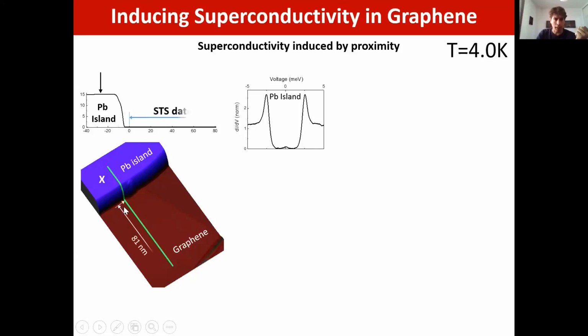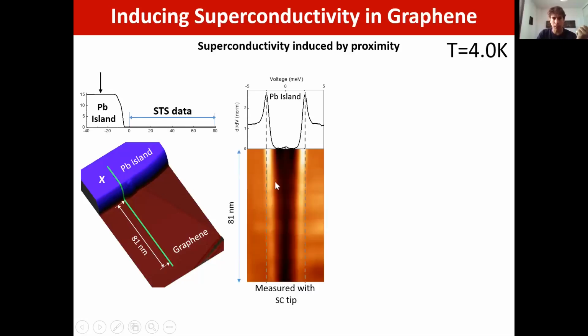So now we wanted to analyze the superconductivity that is induced on graphene. So we analyze the density of states as a function of distance to the lead island, and that's our result. We see that we have the opening of a band gap, and it goes far away from the island. This is more than 80 nanometers away. Those measurements are made with superconductive tips. These help us to go beyond the thermal limit, so we can have better resolution than the one dictated by thermal energy. We can have resolutions of, let's say, below 100 micro electron volts. So that's with a superconducting tip.